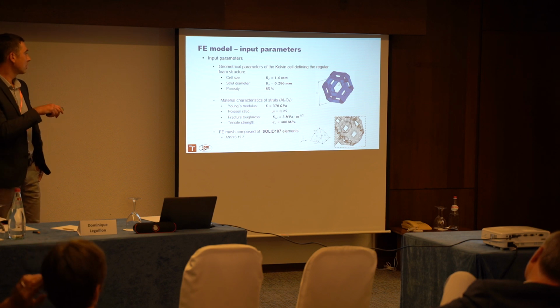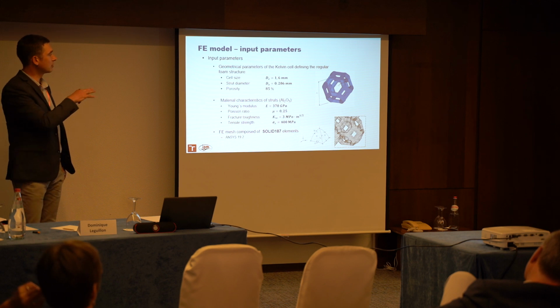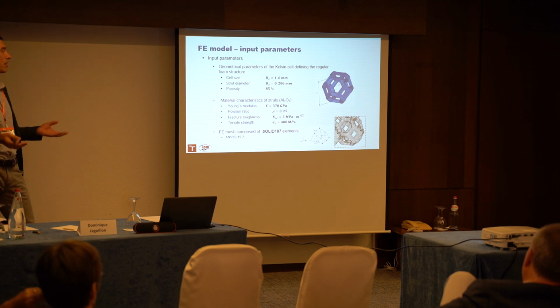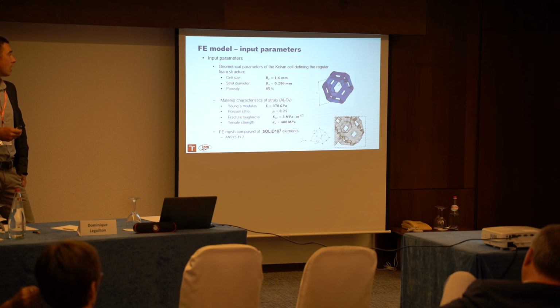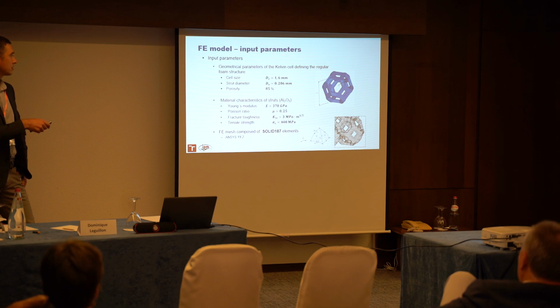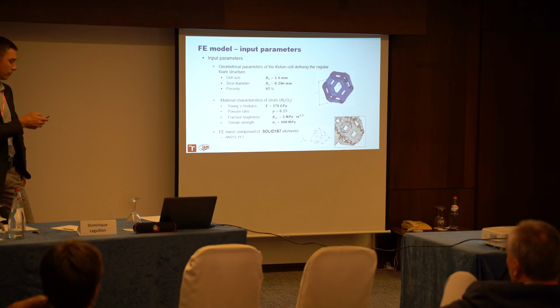It was a Kelvin cell of diameter 1.6 millimeters. We created an array of such cells, and this formed the final foam structure. This was printed using the 3D printer and then tested. So we created the same model with the same geometrical characteristics, and here are the material properties of alumina used in the simulation.